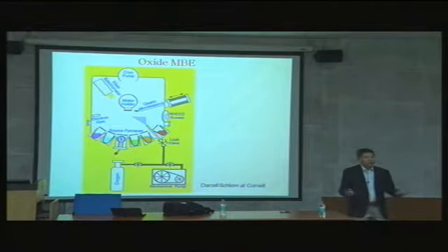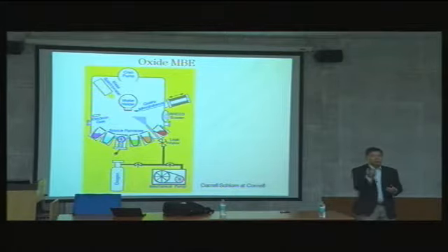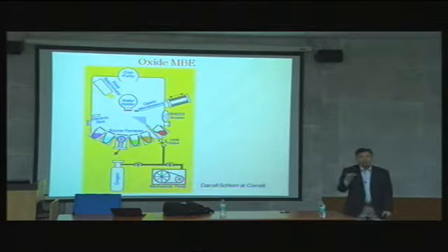Okay? Once you oxidize the source, then you're forming an oxide layer on top of the strontium metal, or whatever metal, and your flux is very unstable because it's covered by oxide. The atomic flux cannot come out of this oxide layer. So you have a very narrow window in which you can bring oxygen in, which means sometimes the materials you grow come out of the chamber very oxygen deficient.